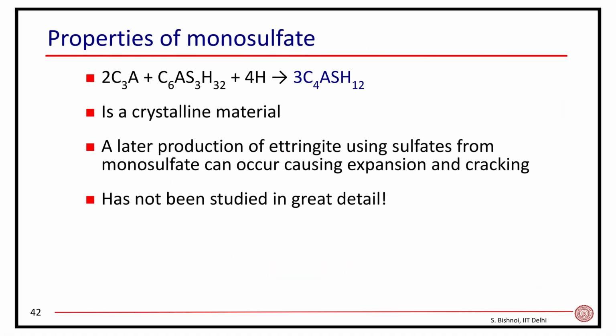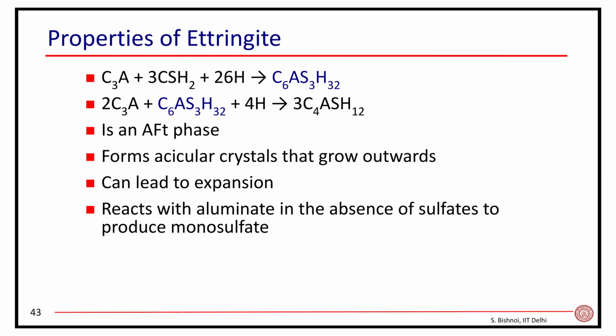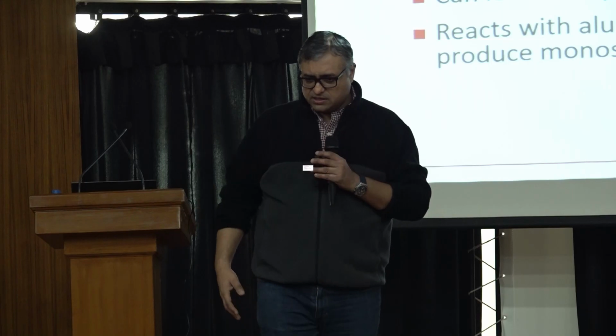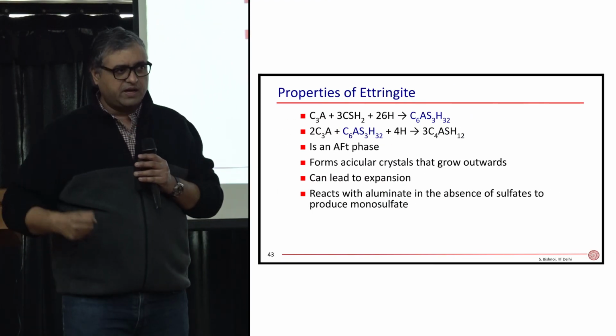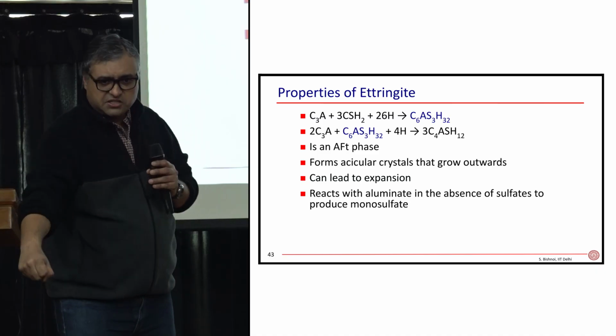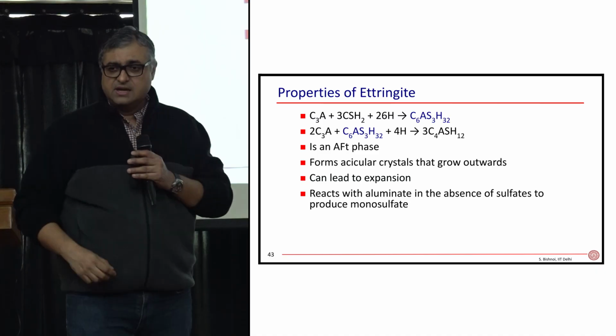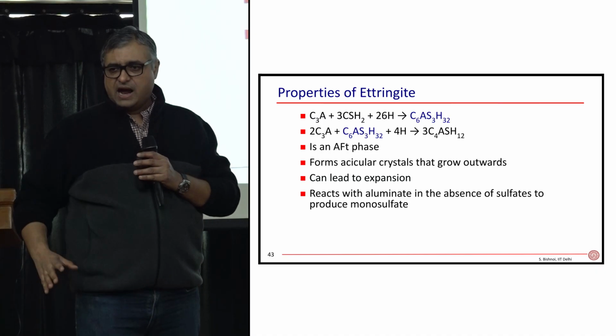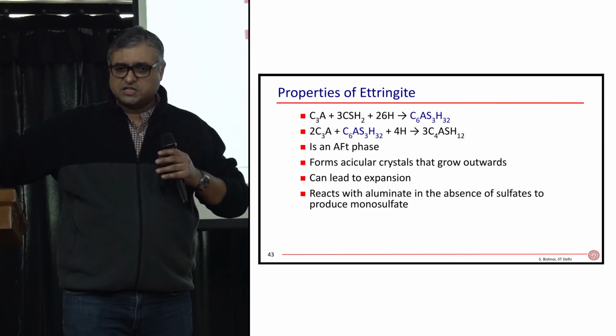The ettringite, the monosulfate, where did the ettringite go? Yeah, ettringite. The ettringite that is produced has needle-like crystals. Now these needle-like crystals, when they're growing in the beginning, see, now my friend Aslam is sitting over there. Let's say he was very close to me. If I produced a needle like this and this needle would grow from here to him, that needle would be pushing him away.